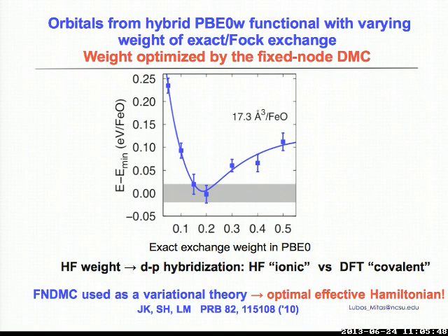And that's a big issue because this is a stochastic picture, so with the error bar it's always a question how much you want to invest into the optimization within a given error bar and how costly it is actually to go down with it. Now what you see here is, if you change this weight, you go from Hartree-Fock, which wants to be very ionic, to DFT, which wants to be much more smooth and much closer to the covalent sort of picture. And note that this is actually a cool thing.